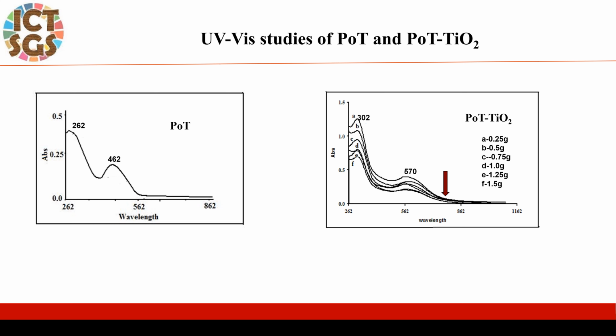These are the UV visible studies. Prepared polymer and polymer metal oxide nanocomposites were studied by UV visible spectroscopy. PoT depicted two absorption bands, that is 262 and 462 nanometer. The first band indicates the substituted benzene due to polar group and pi-p conjugation interaction. The second band is attributed to pi-pi star transition and increases with the conjugation of polymer.